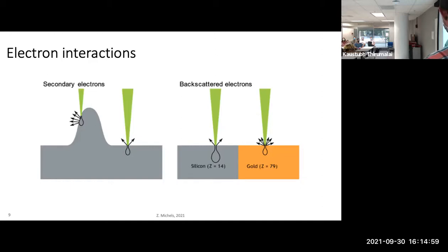So secondary electrons are really strongly influenced by the topography of the sample. If you have a surface that's perfectly perpendicular to the incident beam, you get fewer secondary electrons being generated than if you have a high angle to it, where more of them can escape the surface. So as we make an image of lots of electrons versus not so many electrons, we get an image that tells us about the topography of the sample. Whereas backscattered electrons are more influenced by the density of the material, because that scattering effect has to actually go into the material and come back out.